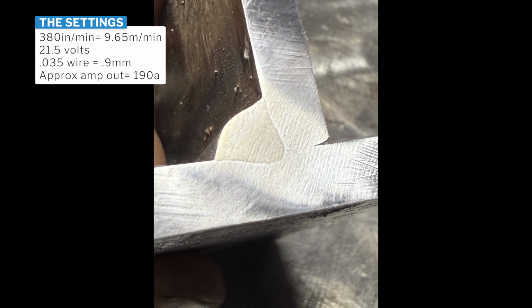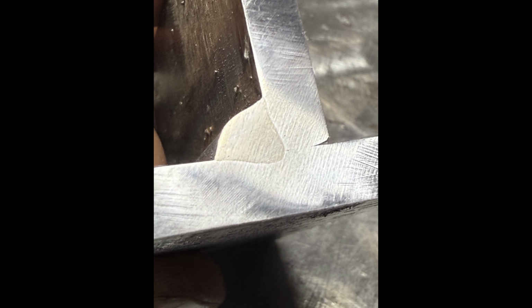The sidewall fusion near the toe of the weld is a little bit less than I would like to see, but this is exactly what you can expect from the short arc MIG process. It tends to favor a little bit more of the root penetration over sidewall. When you use 7018 stick rods, it tends to be a more rounded weld nugget per se, but this looks good. And definitely the short arc process can weld 1/4 inch steel with a 200 amp machine.